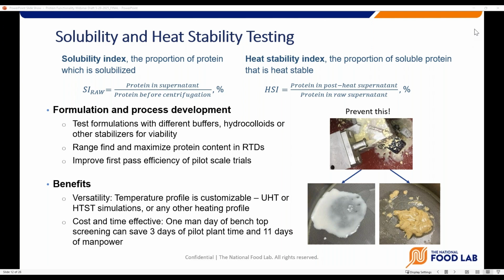The simulated heat treatment can be performed under controlled conditions, and after the treatment, the same sequence of operation used in solubility testing, meaning centrifugation, separation of supernatant, and testing it, will allow us to determine the proportion of soluble proteins that are heat stable or remain in solution after the heat treatment. We also use the process simulations as a prerequisite before pilot scale processing using microthermics to improve first pass efficiency of pilot plant trials. You can see here in the pictures that it helps prevent some of these undesirable outcomes.